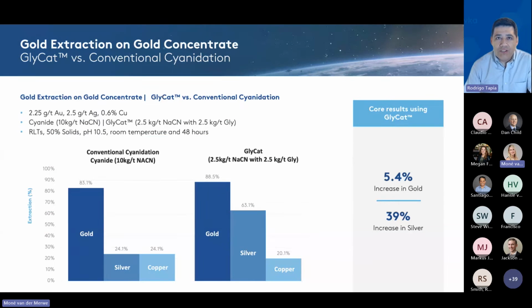Well, let's see now some interesting possibilities of glycat. In this slide, these two graphs compare the traditional cyanidation versus glycat in a typical ore body. The main insights that can be captured here are, at first, glycat represents a significant advance in sustainable gold extraction, with an increase of 5.4% for gold recovery and 39% for silver recovery, respectively. Second, the sodium cyanide consumption was reduced by over 75% compared to cyanidation when using glycat.